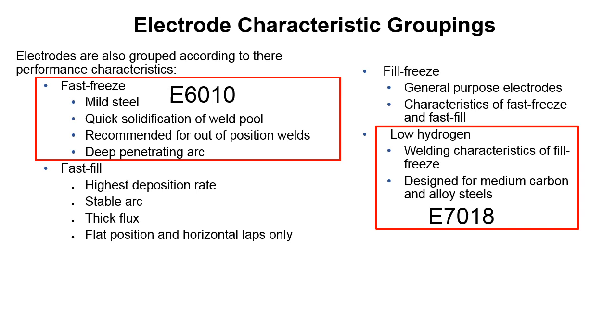And then we go to low hydrogen, which is something like a 7018. These are generally classified as their own little characteristic group, but they act like the fill freeze. They deposit quite a bit of weld metal, but they freeze relatively quickly, but not as quickly as a fast freeze. Low hydrogen electrodes, in my experience, you've got to really know what you're doing when you're welding, or the puddle will fall out on you.